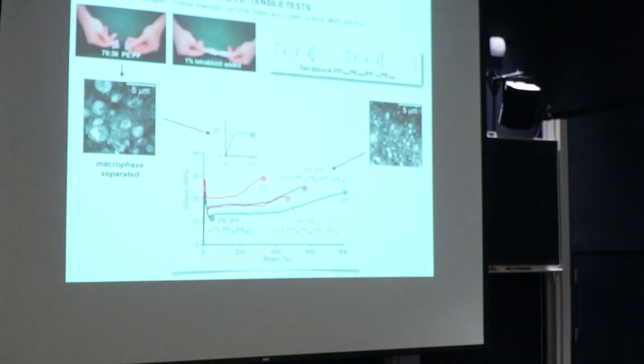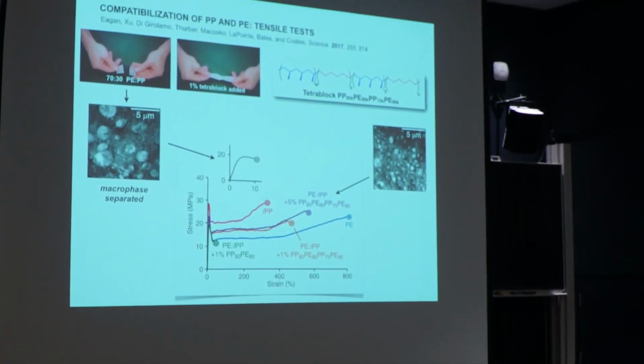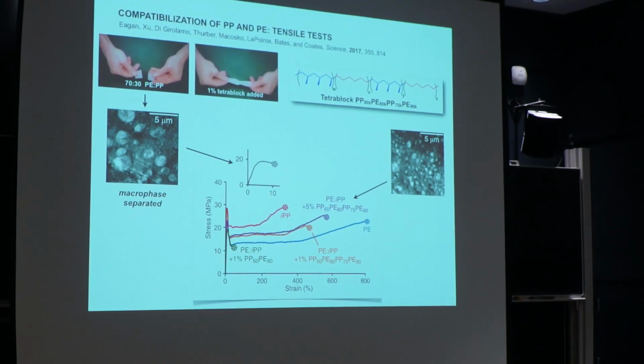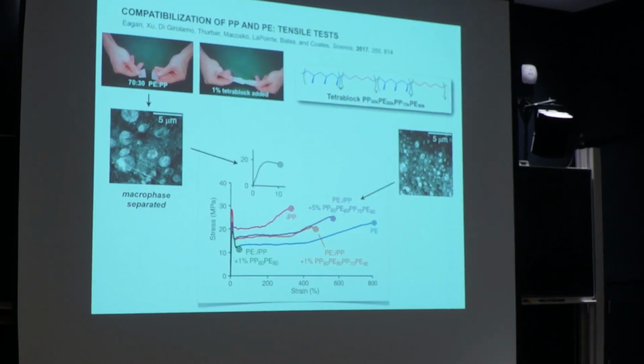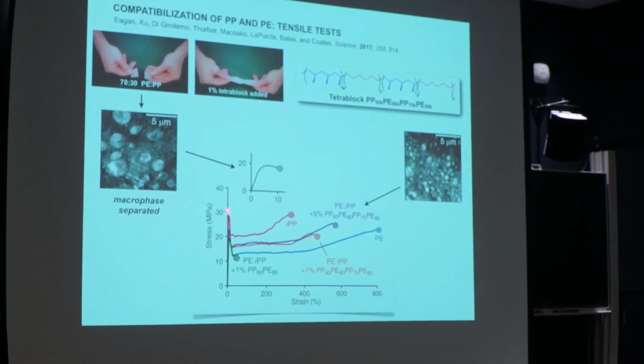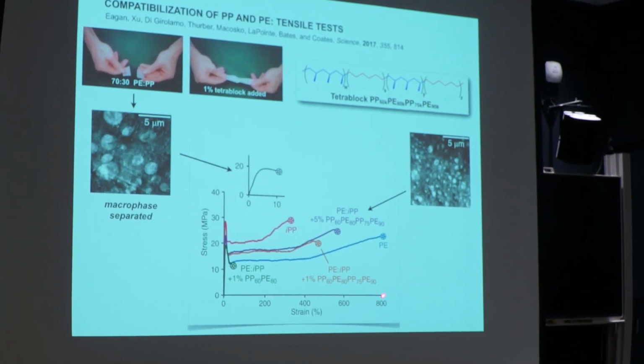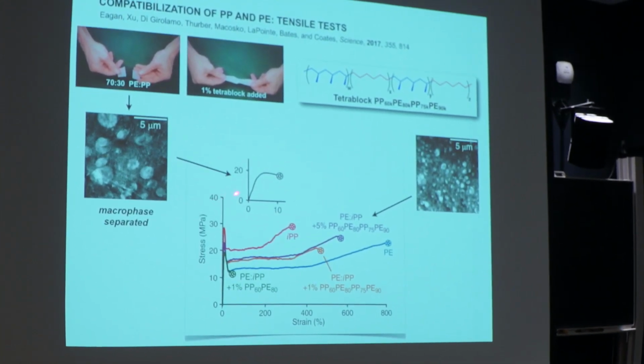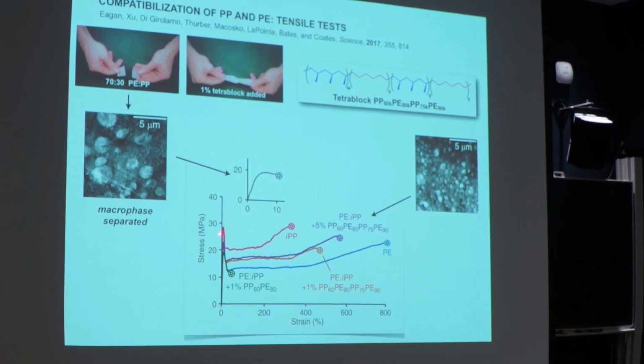1%, that's just 1%. If you go to higher block structures, you can get down to parts per thousand. And then the economics, I mean, you can make things that are really expensive when you're putting in such a small amount. So, a stress strain plot: this is looking at elongation of the material and how hard it is to do. If you just take that material, I had to blow it up here because it's so awful that you look at it cross-eyed and it falls apart.